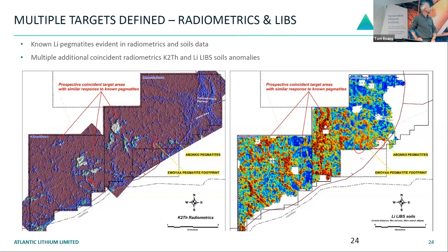And what we actually think is happening is this is also full of mica, and that mica makes its way into the drainages. So it's a resistate. And then when we collect our soils in that fine fraction and then produce the puck, you're actually getting all those micas aligned. So you have this surface of mica that you're analyzing. And I think that's what's actually inflating the samples around Afrangwa and highlighting the drainages. Nonetheless, it is a targeting tool and it has worked for us. It's delivered multiple new discoveries that we've drilled and grown our resource over time. And it's a tool that we're still using now to explore the Salt Pond license out to the west here.